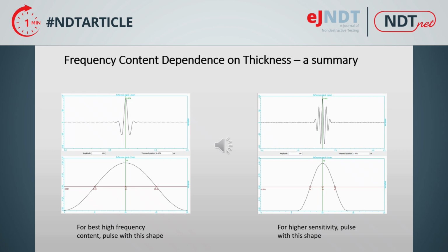Slide 6 illustrates that even relatively high attenuation through thicker sections can be addressed with the proper selection of an initial pulse. So if the higher resolution of a high frequency content is required, the clue is to start with a well-damped, high bandwidth probe and adjust the pulser to optimize bandwidth rather than trying to maximize energy output. When using a negative square wave pulser, improved results will be had by shortening the pulse length and, if available, adding a bit of electronic damping to the pulser.